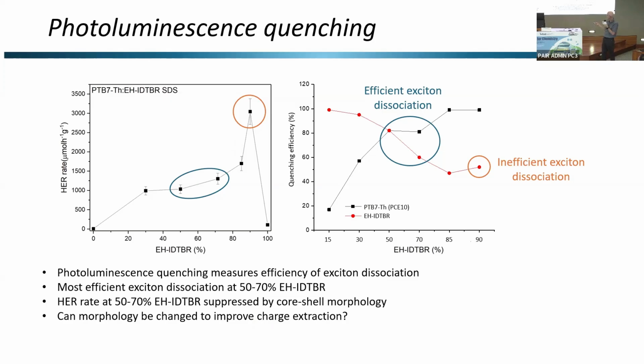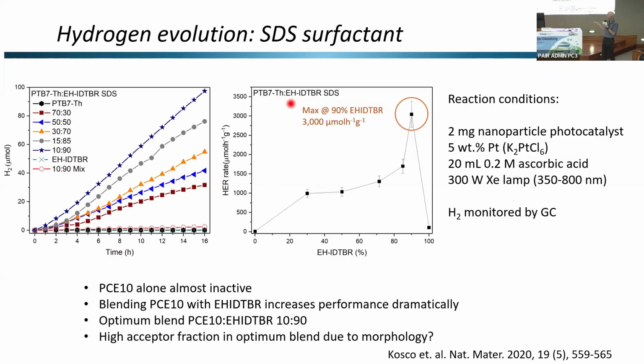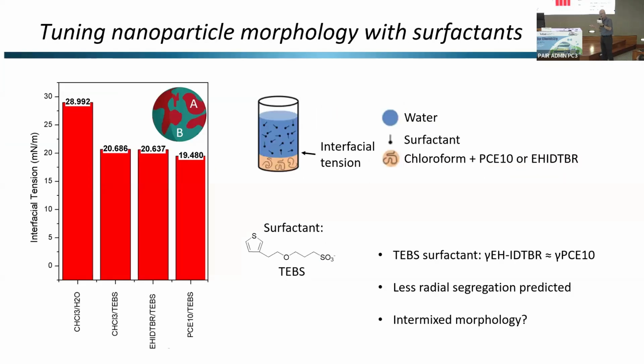And as a result, you know, the HER rate at this point was better than anything out there. So we were quite happy about it, but we thought we could do better. So we started to think, well, how do we try to get a system where there's no preferential radial segregation due to basic thermodynamic considerations? How do we try to find a system where we have the same interfacial tension for the donor and the acceptor? So we looked around and we found this, call it a surfactant, but you can see the interfacial tensions are pretty high, right? So it doesn't really work particularly well as a surfactant, but we have our head and a little bit of an aliphatic tail.